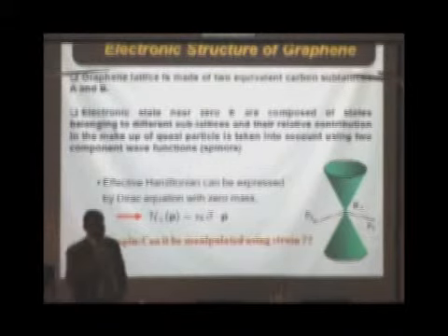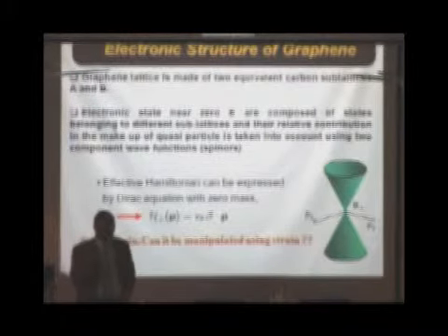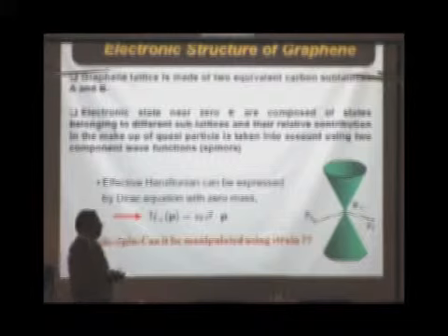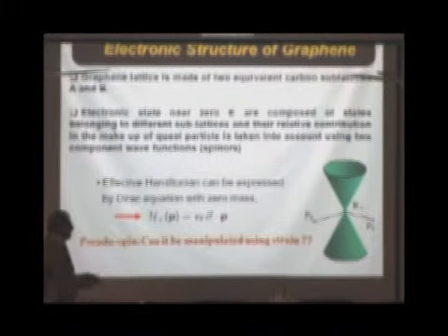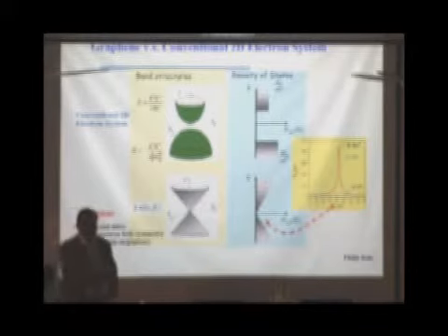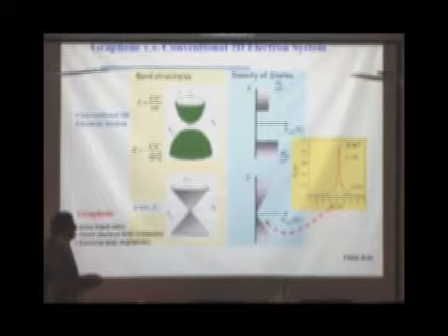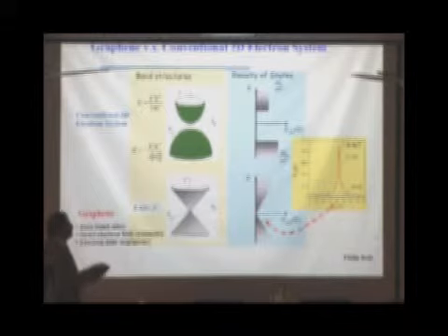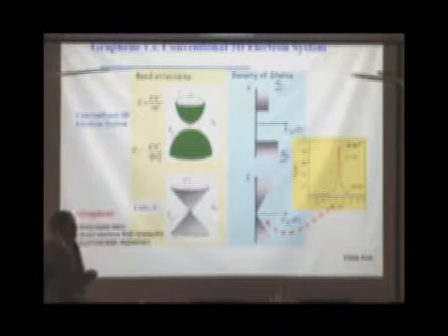So in graphene, you have effective massless electrons, which move with a Fermi velocity, and there are many consequences of this simple fact which are being explored. This is from this review article. I just say that this is for a conventional semiconductor or a metal, and this is for graphene. Because of this, it's a high school textbook exercise to show that the density of states will be linear in energy. Again, many interesting consequences come as compared to a conventional 2D electron gas, and this linearity also is at the back of many interesting physics.